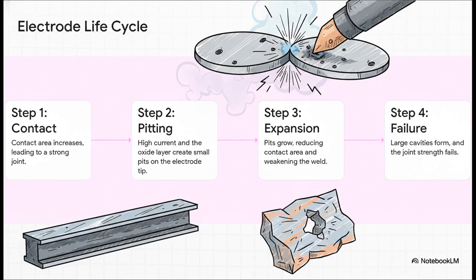At first, things work pretty well. But pretty soon, those extreme conditions cause little pits to start forming on the electrode tip. Then the pits get bigger, which reduces your contact area and weakens the weld. And finally, you get these large cavities, and the electrode just fails. You end up having to replace them way more often than you would with steel.